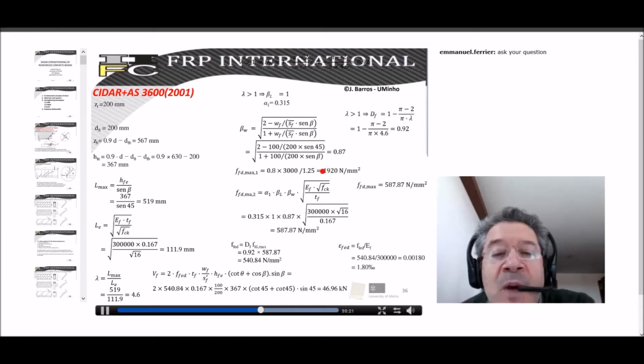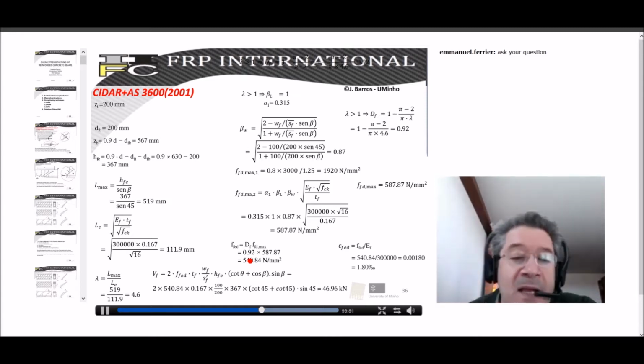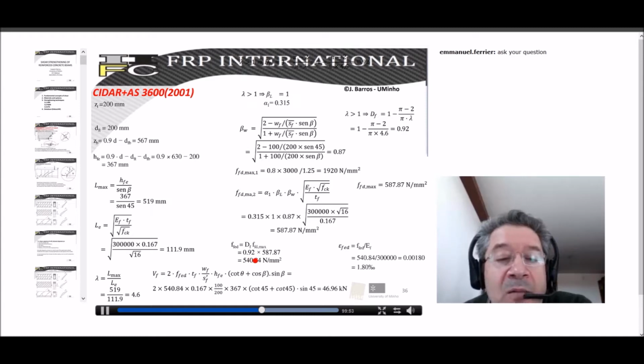These values in this equation, and well, the minimum one, look, the first one we obtain 1,920, and in the second one we obtain a value that is around 588 megapascal. So this means that the value that we should adopt is about 590 megapascal, and then this value is finally replaced here in this equation, and then we obtain the design value of the effective stress installed in the FRP.